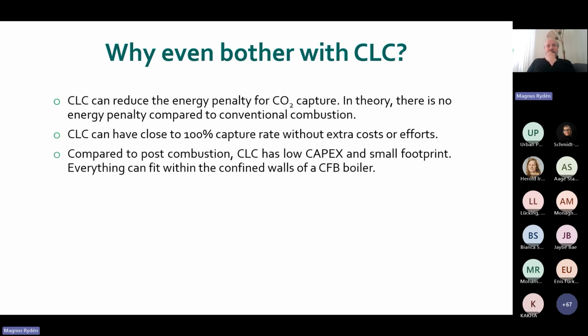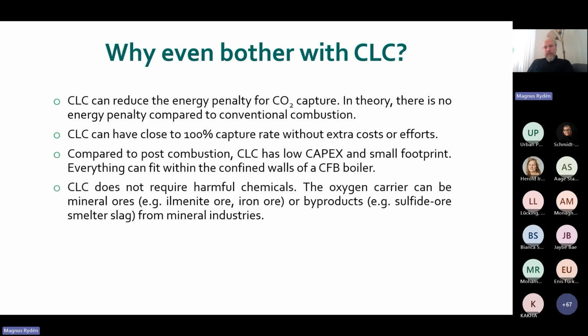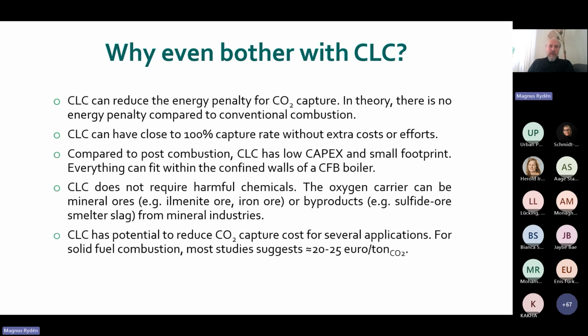We can achieve low capex and a small footprint. As we have seen, the size of the facility will be the same as our regular CFB boiler, and capex correlates largely with size. We don't need any harmful chemicals. The oxygen carrier we would want to use is probably a mineral ore concentrate like ilmenite, which is iron titanium ore, or some iron ore, or even some byproduct from metallurgical industries. And there are many studies trying to calculate CO2 capture costs, and they usually end up somewhere in the range 20 to 25 euro per ton CO2, which is at least 50% cost reduction compared to amines.